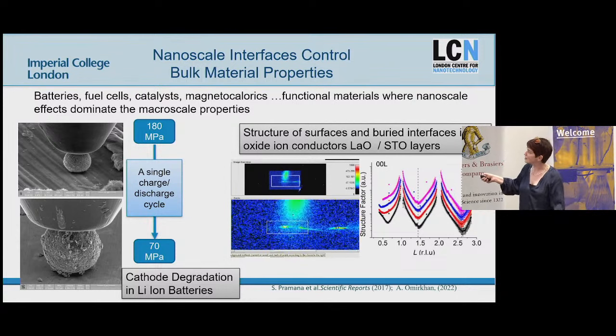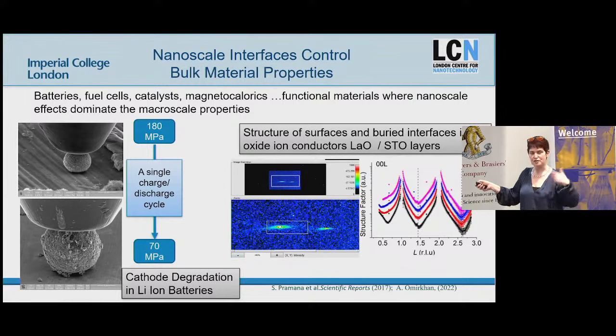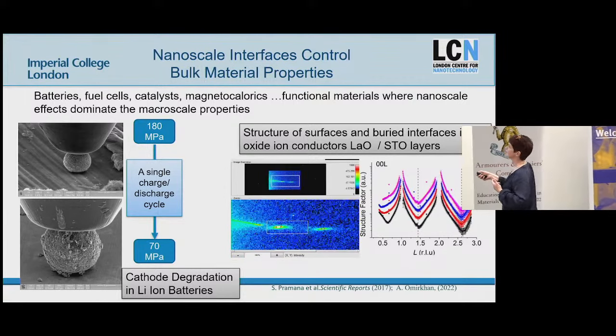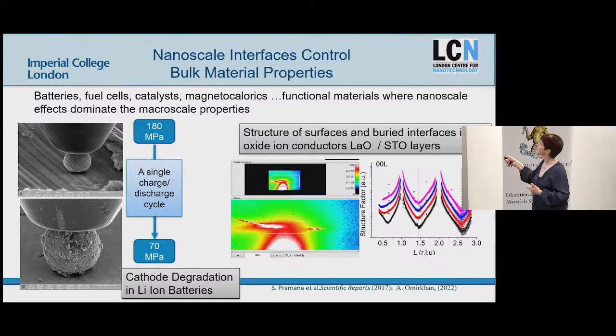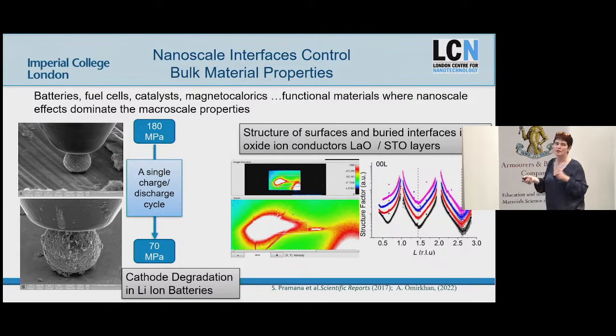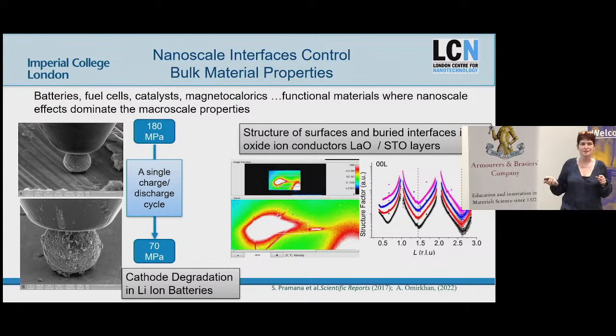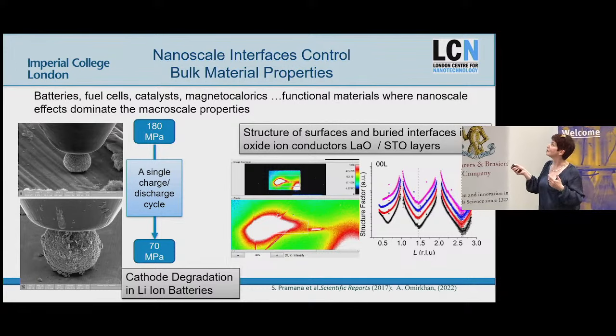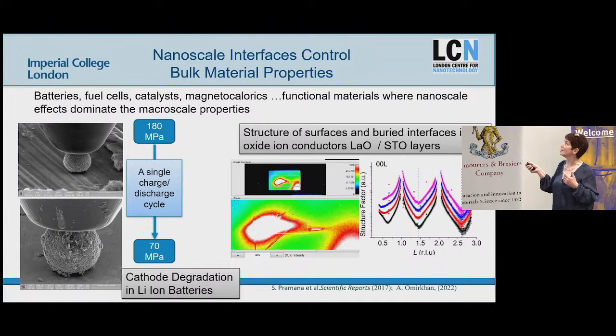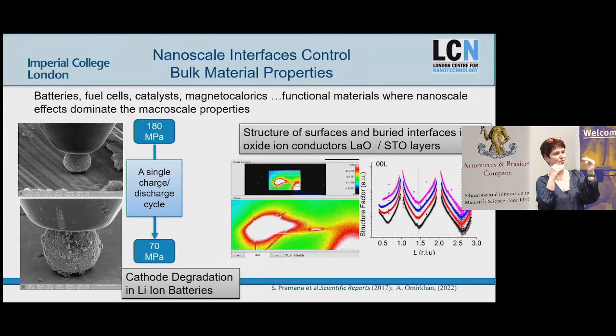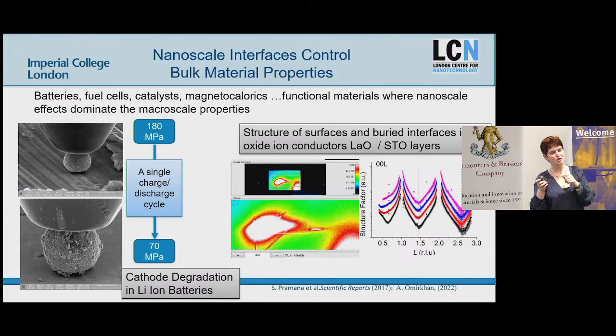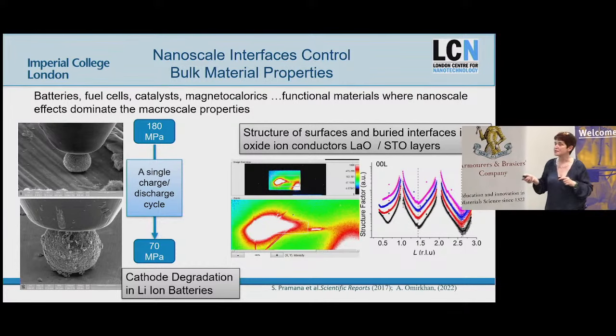And we can do this in operando. So this is the Bragg peak here. The big guy is the Bragg peak. This little guy is going between the Bragg peaks, and you're seeing scattering. You're seeing intensity over time until you get to the next Bragg peak. So you're going from here to here to here. Those of you with an eagle eye will notice there are two Bragg peaks here, right? What that tells you is my lanthanum oxide, my LaO, and my STO are very crystallographically aligned, right? These are epitaxial, so their Bragg peaks sit next to each other, right? But what's interesting is what you find out between the peaks, right?